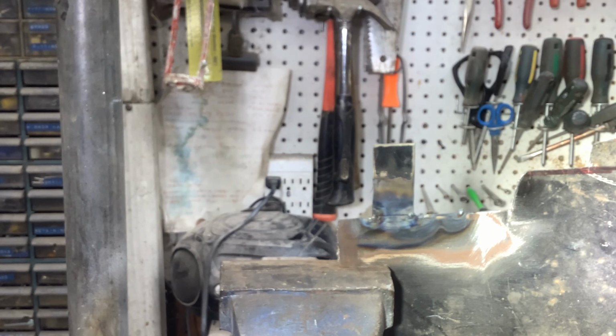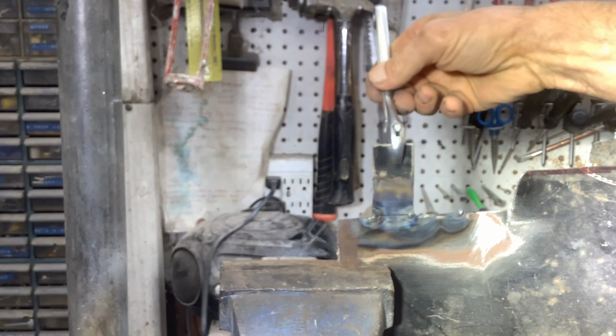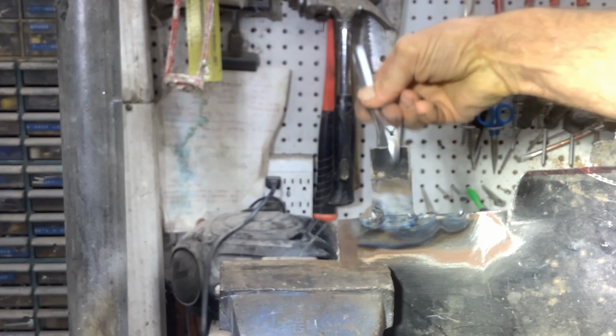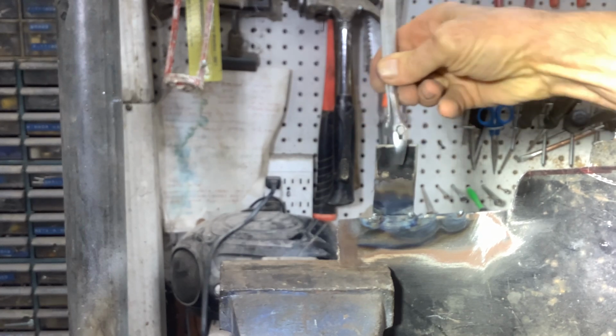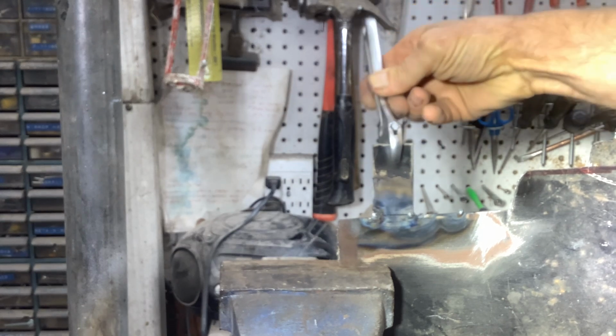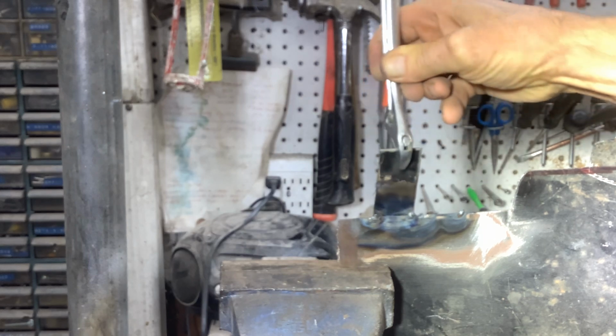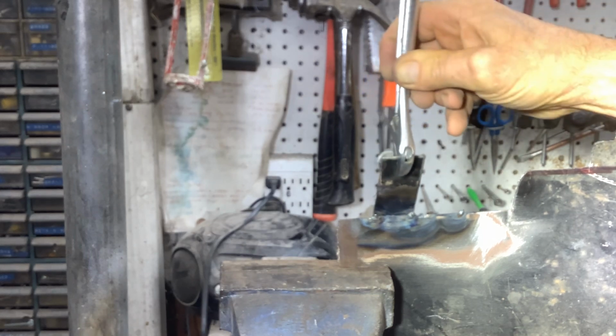Okay, that tack weld failed with just a few twists. About 3 twists. Now this is the annealed one. Starting to fail, but it's taken a lot more twists. It's still holding. I think it's broken on one side and it broke on this other side. So you can see that it took a lot more twists to break the weld.